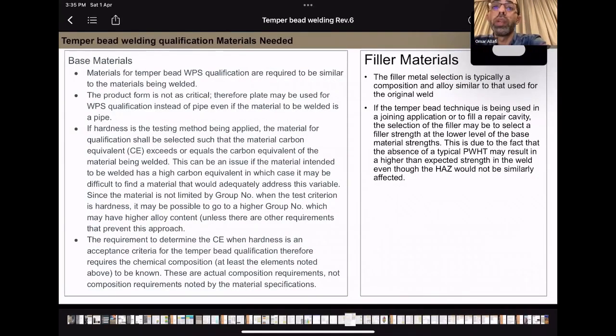Okay, so temper bead qualification, the material of temper bead qualification should be similar. We should have the same WPS. The product form is not critical. The plate may be used for WPS or pipe. If hardness is specified, then you have a carbon equivalent, and this carbon equivalent might have a problem when selecting a piece as a test coupon, because you need to take a higher carbon equivalent value. But this can be resolved by changing the group number. In the case of hardness, the group number is not an essential variable. So you can change the group number and select a test coupon with higher carbon equivalent to qualify your WPS.